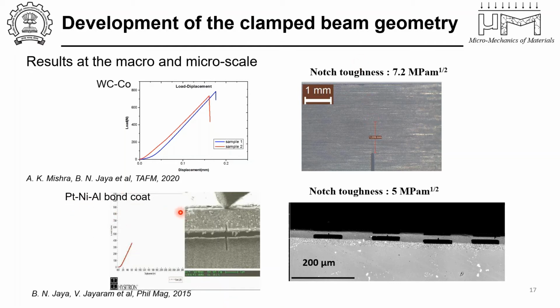In the bond coat, like I said, the video that I already showed, for that particular specimen, we could measure a fracture toughness of about 5 MPa root meter. So all of these we applied as of now, as of today, only for linear elastic fracture mechanics. We are in the process of developing the same for elastic plastic, but we have not made much headway there.